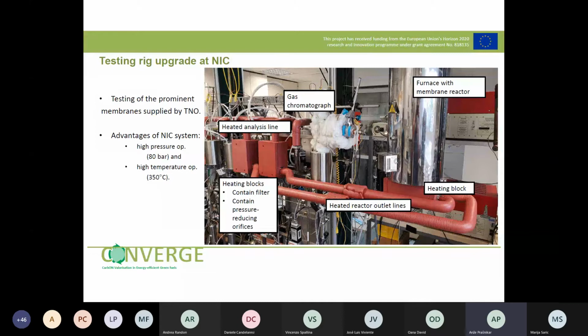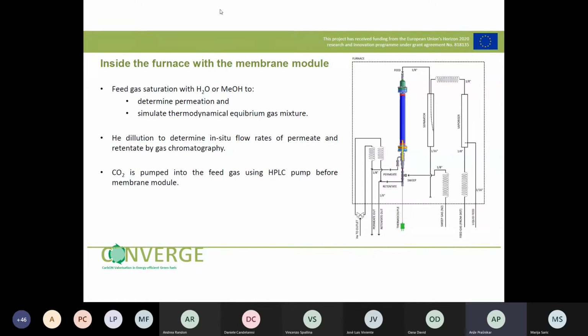On the right side of the figure is the furnace with the membrane reactor, which is shown in more detail in the next slide. This is a scheme of the setup inside the furnace, with the membrane module by TNO. Since we need to determine the permeances of all gases, the methanol and water is pumped into a vaporizer into the preheated flow of the feed mixture. In addition, there is a separator downstream to ensure that only the gas phase enters the membrane reactor. To determine the flow rates of retentate and permeate gases, we dilute the gas with helium to recalculate the flow from gas chromatography. The feed gas mixture with methanol and water can also be used to simulate the equilibrium mixture as in the TNO setup to efficiently use the membrane reactor.